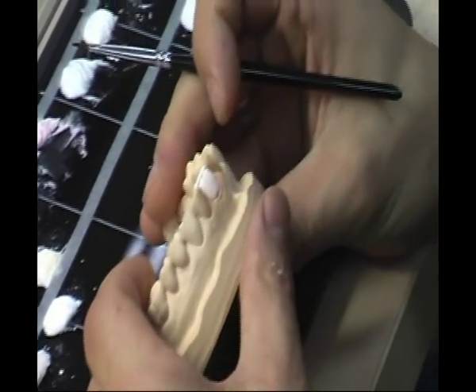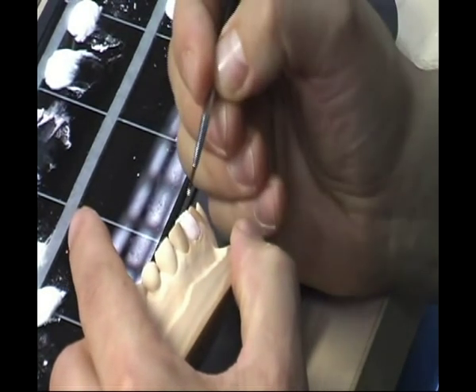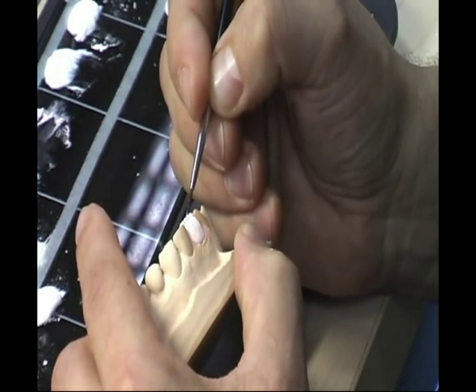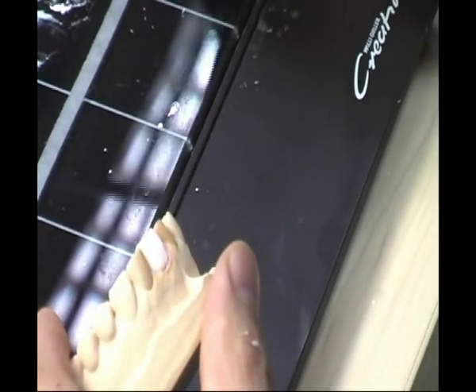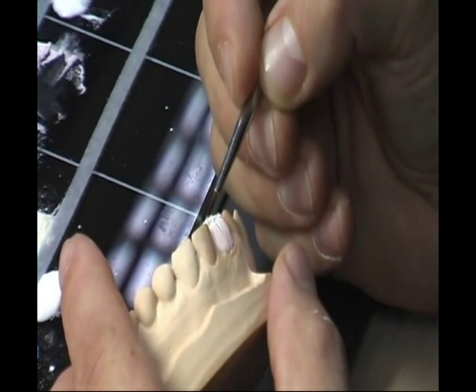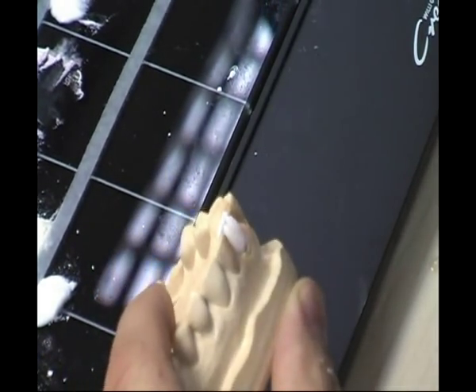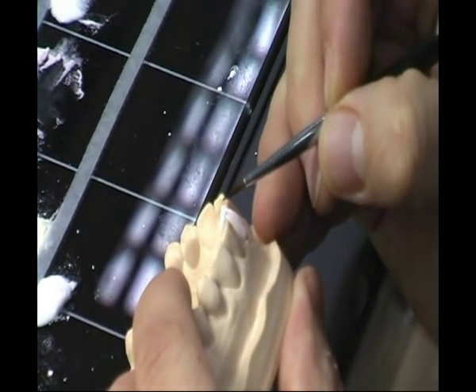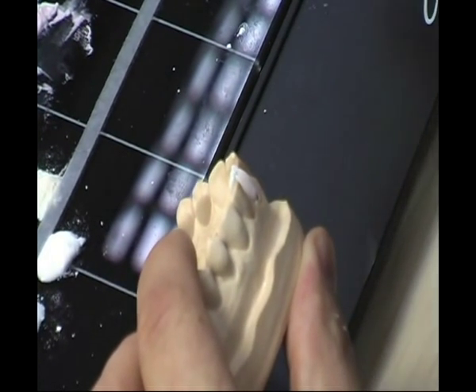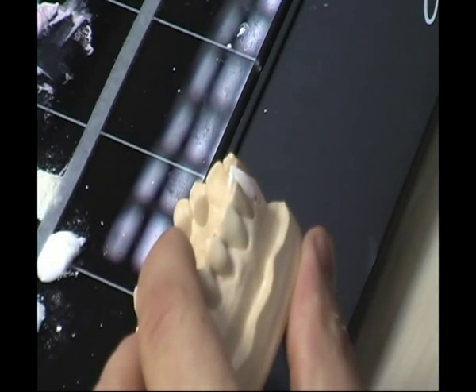Then we also have to respect the shrinkage. The shrinkage is about 0.8 to 1 millimeter with this ceramic. The retraction is about 1 millimeter, which we will have in zirconia, after shrinkage. This is now the palatal shield. You have to know how much the ceramic shrinks, and build up so that it comes back to exactly what you want.